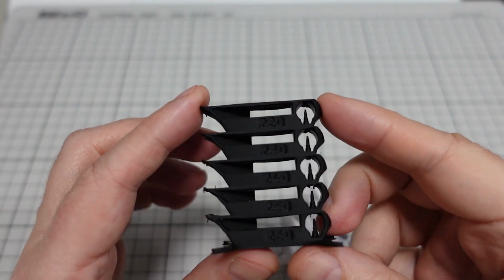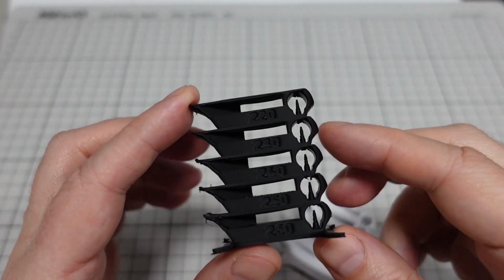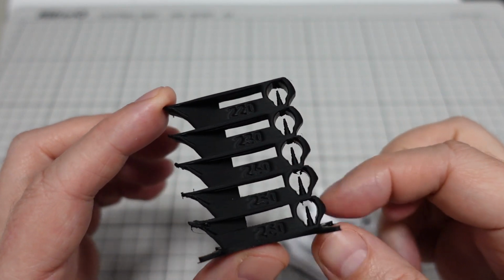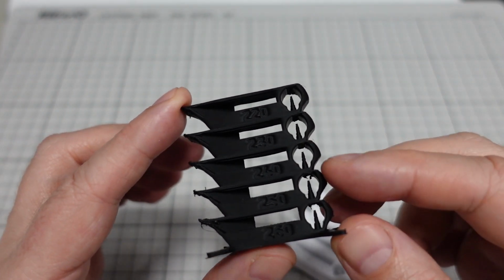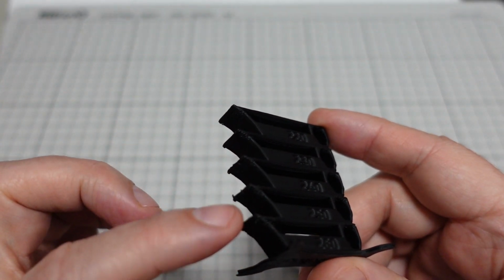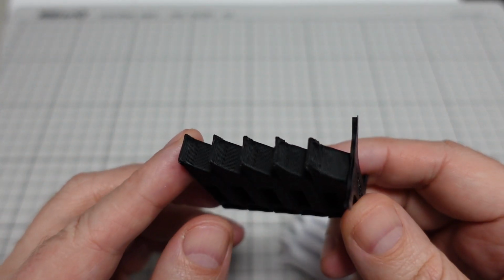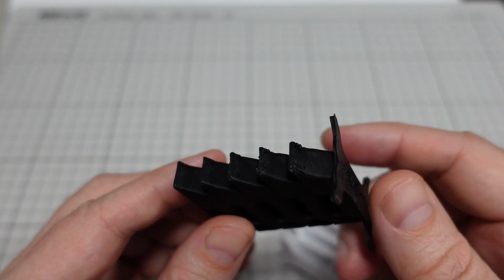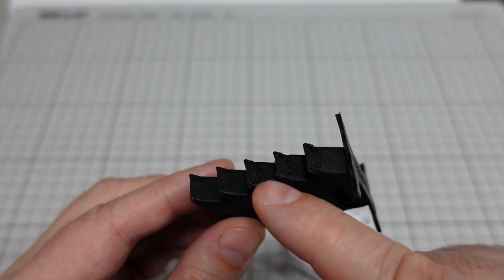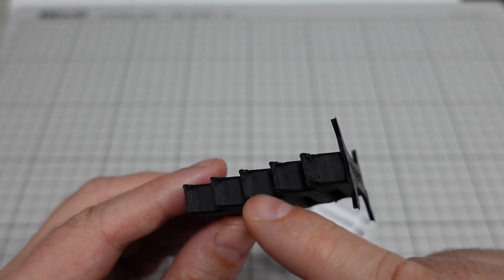And if I analyze this temperature tower, the bridging is almost equal on any temperature, and there is no stringing. Usually that's not even the problem with ABS. But I see that there is a difference in overhang. And if I would analyze these temperature towers, probably I will choose the 240 degrees Celsius for the printing.